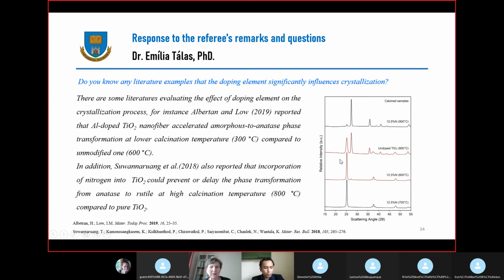Oh, okay, thank you. I also have an example in my practice. Tin as a doping element also decreased the temperature of the rutile formation. So in that case, the main reason is that tin oxide also has the rutile type of crystal, and it behaves like a seed for rutile formation and for the phase transformation. Yes. And let's go further.